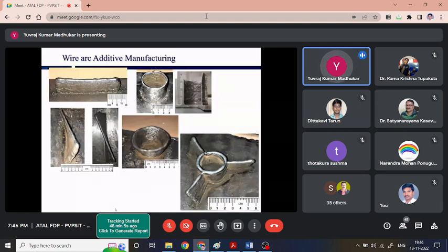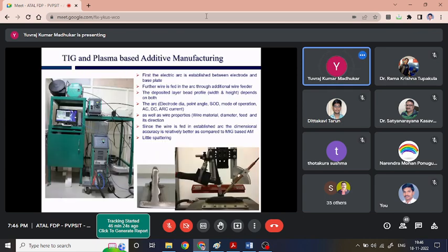Once we could optimize the parameters, you could see over here such beautiful shapes we could deposit, no problem at all. Here, even in the case of a WAAM application, we could deposit a wall thickness of the order of close to just 2 mm. Some fulcrum shapes, which resemble propeller shapes, we can deposit very easily.